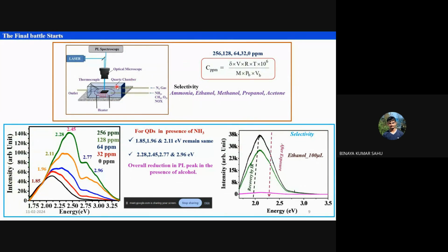So this is the experimental setup that I have already explained. This is the stage where the material like tin oxide will be kept, and here the ammonia will be passed through. And as I have told, now more or less you people have some idea about the PL spectra. So this is a PL of the tin oxide when there is no ammonia. But when you are giving the ammonia, slowly these two mysterious peaks, basically this 2.77 and 2.96, started enhancing. Later on we'll see why their intensity is increasing in the presence of ammonia, whereas the other peaks like 1.85, 1.96 and 2.11 are remaining silent. So that part we'll be seeing. Okay, so this is the sensing data basically.